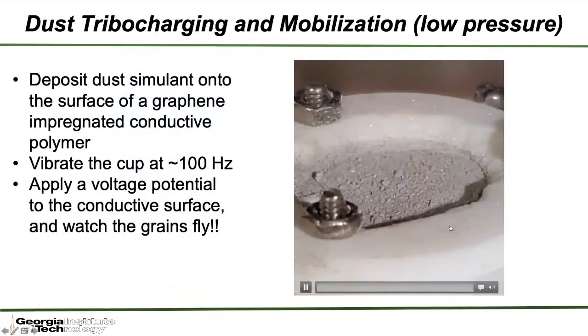And so here's a video that I took showing the cup where I'm starting to vibrate these grains around. Now this cup that I'm showing here doesn't actually have the holes in it. We wanted to just see if we could get these grains charged without dropping them down first. So what we actually did is we installed a sample of conducting polymer, which is being developed by my PI and collaborators as a potentially conductive spacesuit material.